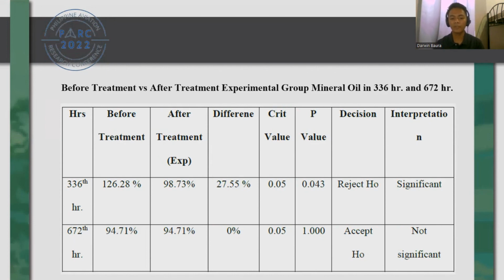And lastly, before treatment versus after treatment, mineral oil has an interpretation of significant at 336 hours, but not significant anymore at 672 hours. This is because the p-value of mineral oil at 672 hours is higher than the critical value now.